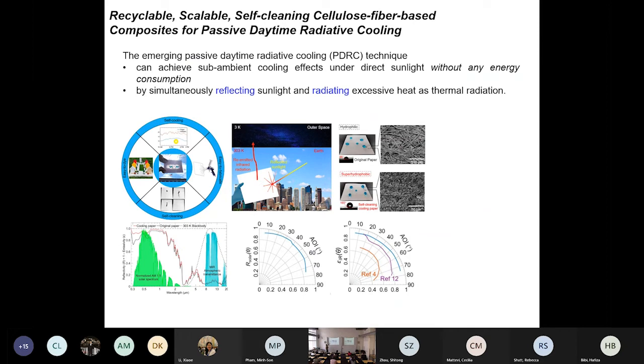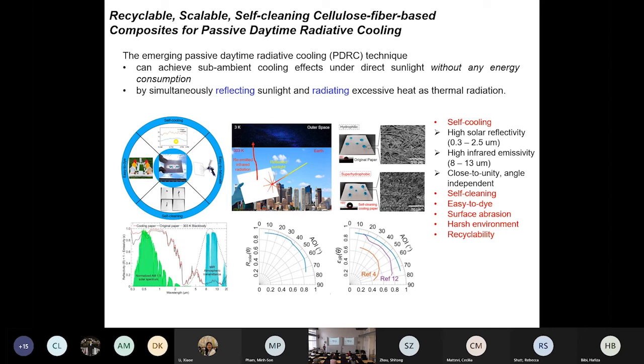Like I showed you here, in passive cooling technology the white paper, or the surface of the paper, can reflect most of the sunlight, and it can also emit infrared wavelengths through the atmosphere. The material itself may not be white; it can be any color, and we demonstrated that. The common sense is that white paper has really high reflectance, but it doesn't matter. We can still have red dyed, green dyed, or blue dyed paper. It might affect the solar reflectance a little bit, but the cellulose fibers themselves still have really high infrared thermal emittance.